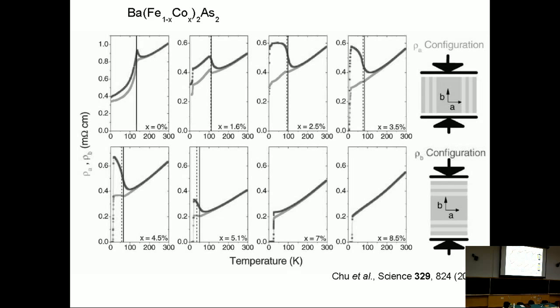And for relatively small strains, it is found that the resistivity measured along the strain and perpendicular to the strain are quite different, and that depends on doping. So for 0% doping, just the pure material, you already have some difference in the conductivity. When doping starts, you see more pronounced differences between the resistivity in both directions. And when superconductivity shows up, again, the system becomes isotropic, but you can note that for some intermediate doping regime, the difference between the resistivities can be quite large, a factor of 2.